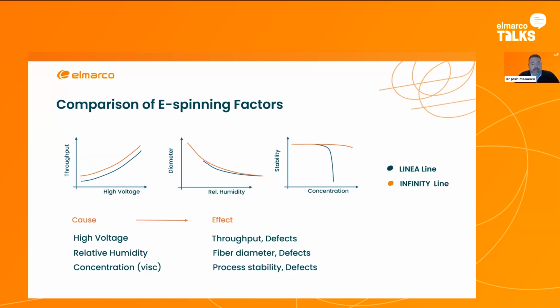We also see that through this extra stability, we've been able to have a bigger spinning window. What we call a spinning window is the ability to spin at higher or lower concentrations or higher or lower relative humidity. And those directly impact fiber formation. They impact fiber diameter mainly. And if you have a bigger window, it allows you to push the fiber diameter further down or further up in the process, and then also be able to spin, sometimes even spin materials that aren't able to be spun on our LINEA technology, which was a benefit we weren't expecting necessarily. It wasn't the goal.